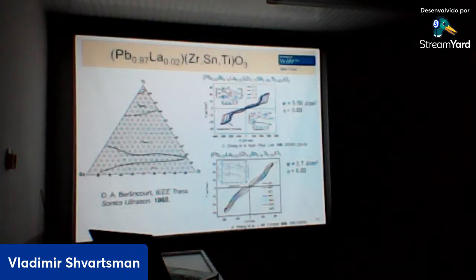Field about only 300 kilovolt per centimeter in comparison to 600 in the lead zirconate, and about 5.5 joule per centimeter cube the stored energy density. But what is not good for antiferroelectrics, sometimes this hysteresis is too broad, and therefore the efficiency will be low. So you see, efficiency here is only 0.7.